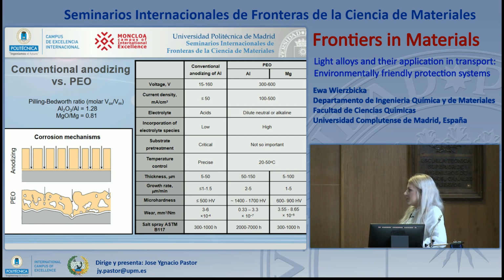Also, there is a difference in corrosion mechanism. Through the almost through-hole pores in the conventional anodizing structure, the corrosive media can much more easily reach the substrate. It is protected only by the barrier layer. In the case of PEO, we have some pores, but they are closed on both sides, so this process goes not so easily.